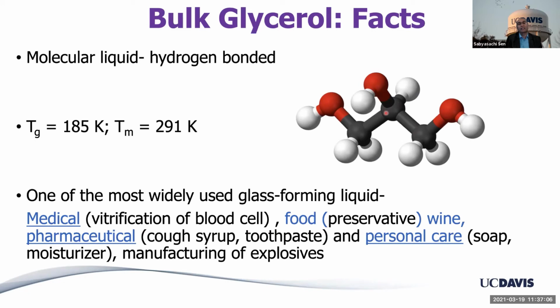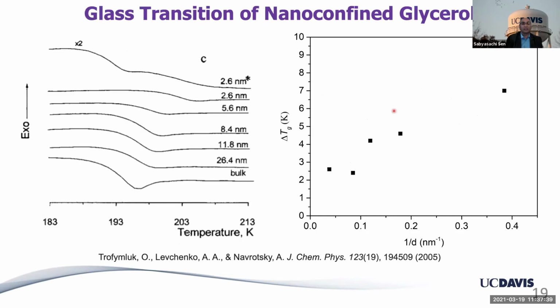So we did a site selective enrichment. Not we, but we bought the chemical, which is enriched in this CHOH site. These are CH2OH. This is the only CHOH site. So we'll be looking only at this carbon. And we'll be looking at the dynamical averaging of NMR interactions because of the anisotropy of the NMR effects on this carbon atom as they get averaged as the molecule tumbles and rotates in liquid state.